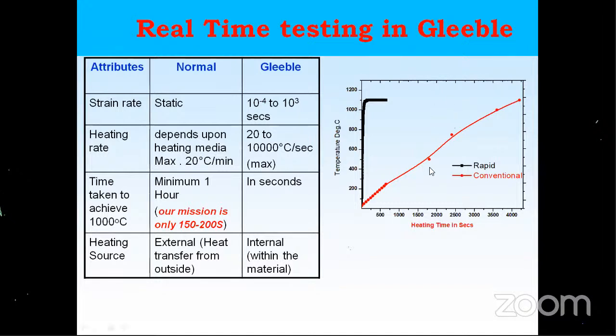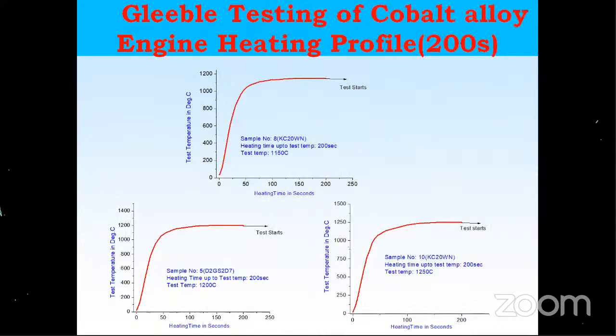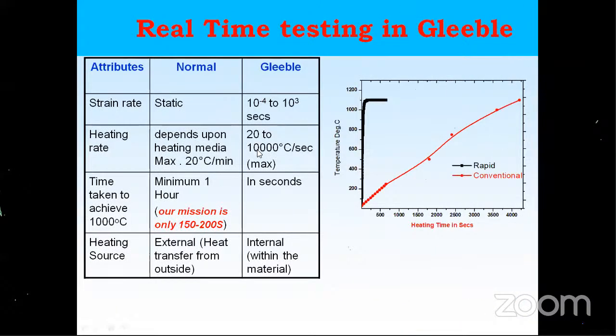So here the conventional testing is like this. Heating time takes a lot of time, almost 4000 seconds. Whereas, suppose I can test within 10 seconds, then my material property will be a different thing, I'm sure. So let us see. I have installed a machine called Gleeble, where my heating rate is almost 10,000 degrees per second. So with that, I could do the test.